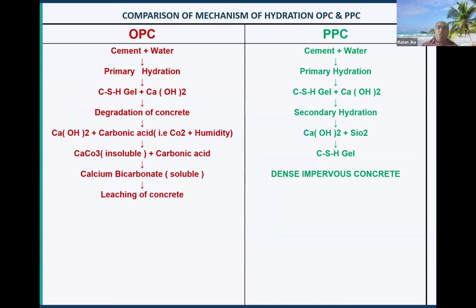What are they? If you compare ordinary Portland cement versus PPC, cement plus water in both cases, primary hydration occurs in both cases. After primary hydration, what happens? CSH gel is formed and calcium hydroxide is liberated. In PPC also calcium silicate hydrate gel is formed and calcium hydroxide is liberated. Up to here, the similar chemical reaction happens in OPC and PPC. After that, in OPC, what happens? Degradation of concrete starts. Why? Because the liberated calcium hydroxide stays within the concrete.